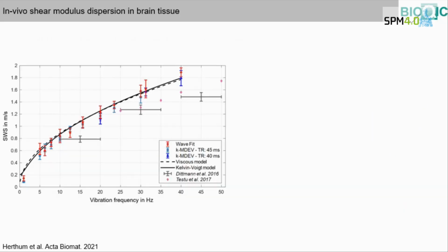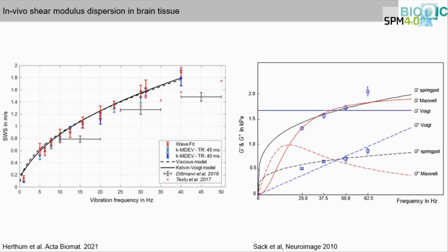And the shear wave speed here plotted over frequency in a group of volunteers compared to the literature described here, such a power law which can be fitted by the Springpot model. This is a lot of old work, actually, 2010, where we compared at this time only 4 frequencies, 25 Hertz to 62.5 Hertz. So we performed multi-frequency MRE in a superimposed way. We had 4 frequencies in those days.